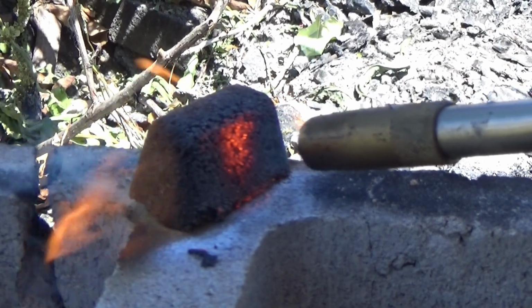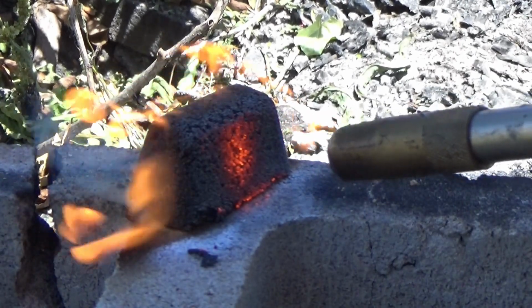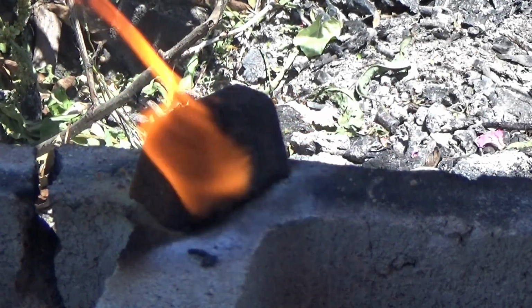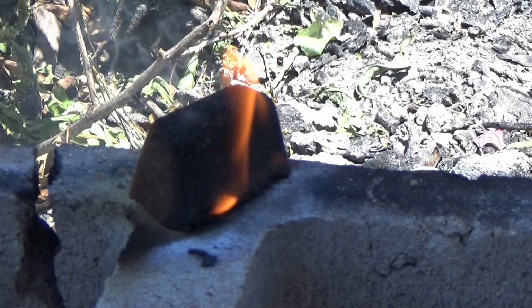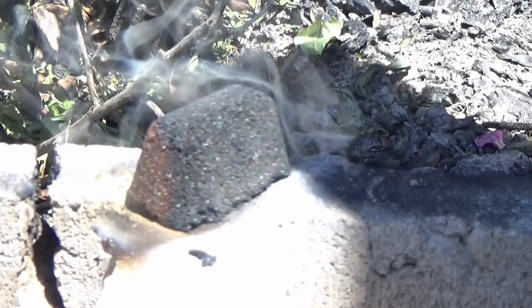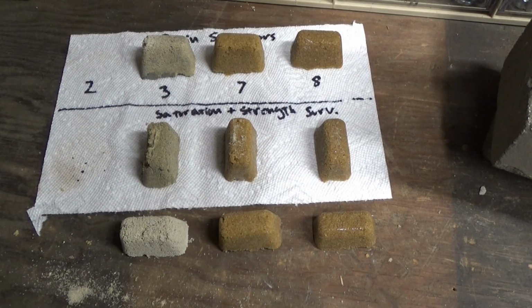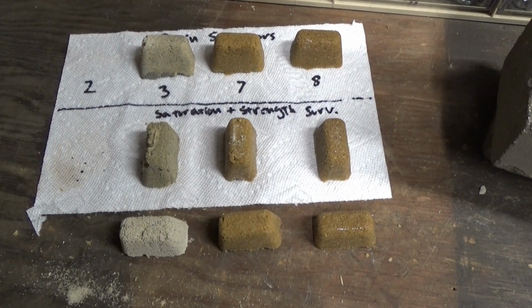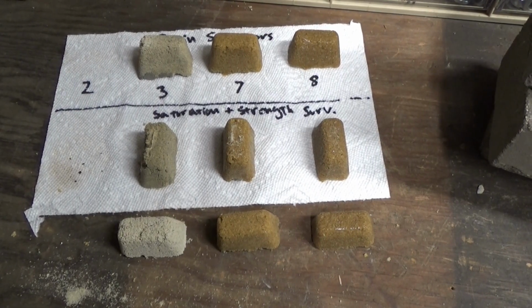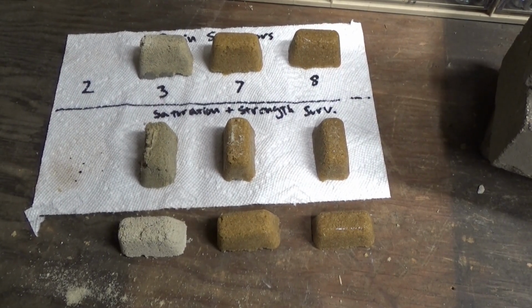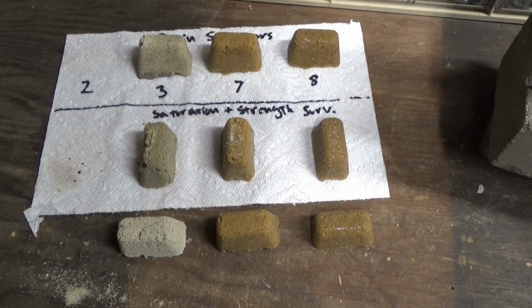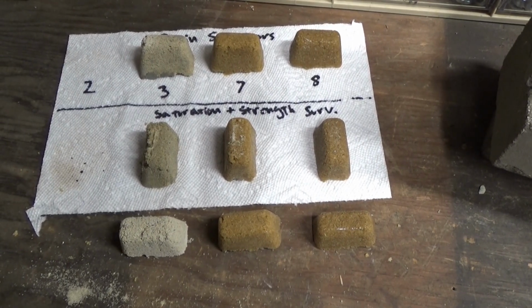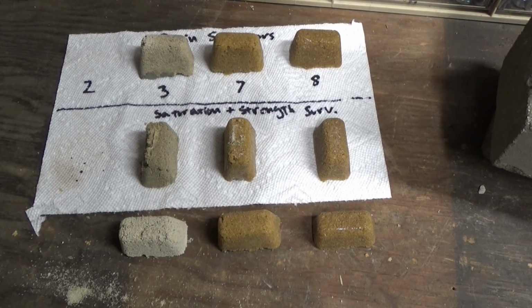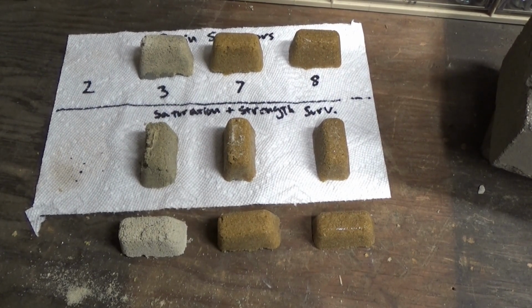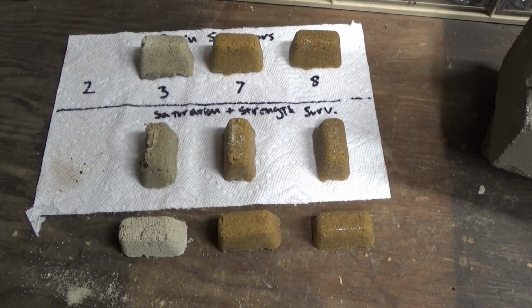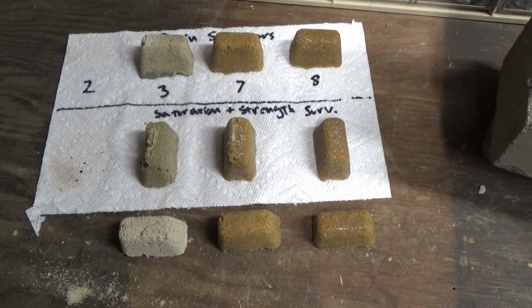As you saw in the fire resistance test, that Portland cement was the only real winner there as well. Both of the other mixtures that performed high in every other test actually caught on fire. So they're not good for certain uses like, say, a fire pit, but they might be good for other uses where the Portland cement isn't as good, such as a sculpture where you want that more yellowish color. Portland cement just looks like cement. It's kind of gray. If you want to build something like a permanent sandcastle, you might want it to look a little more like sand. I did notice that the 100% silicone adds a slight odor to the final product. If you hold it right up to your nose and sniff, you can definitely get kind of a rubbery smell.